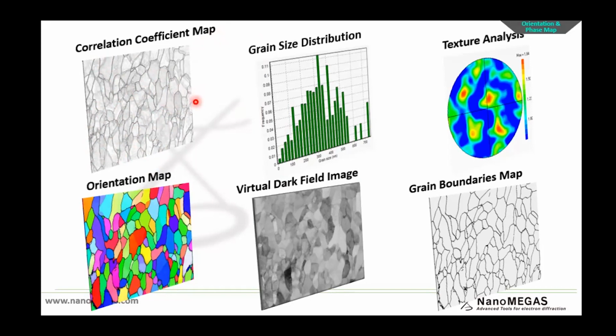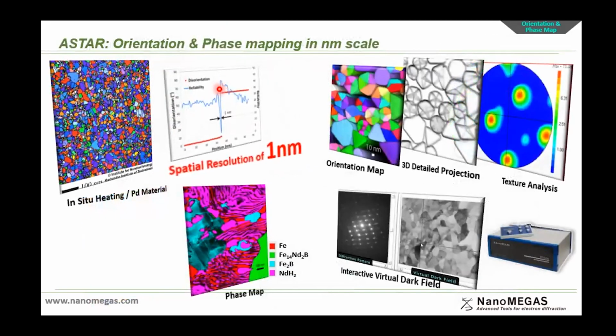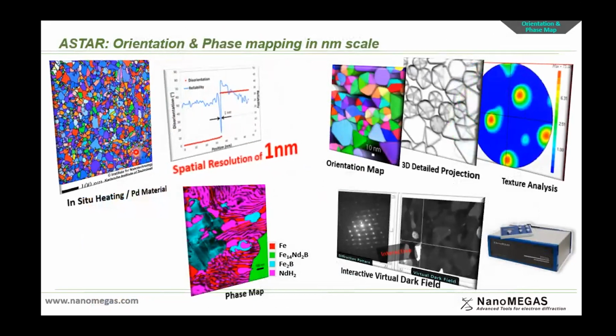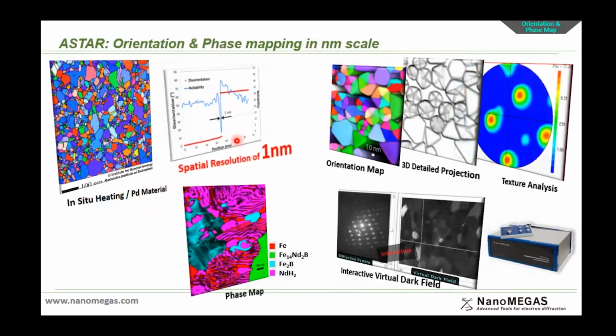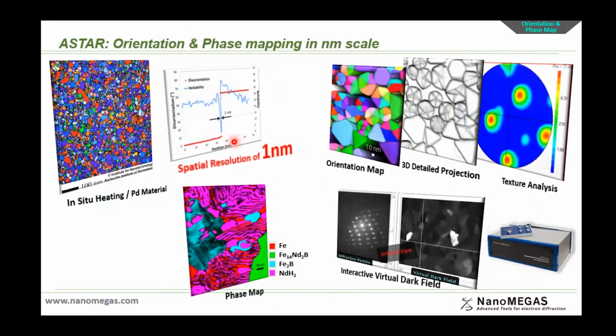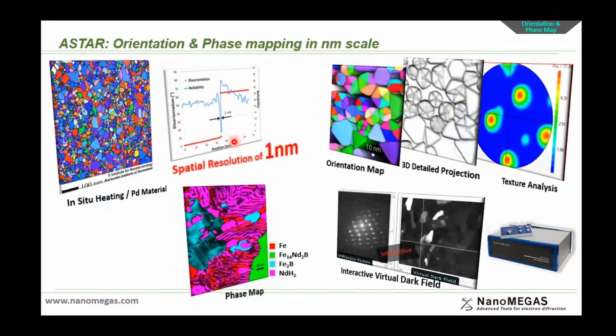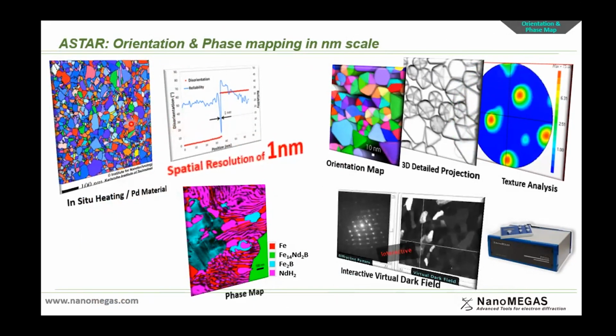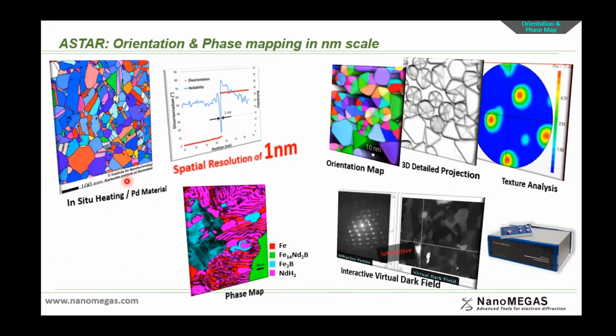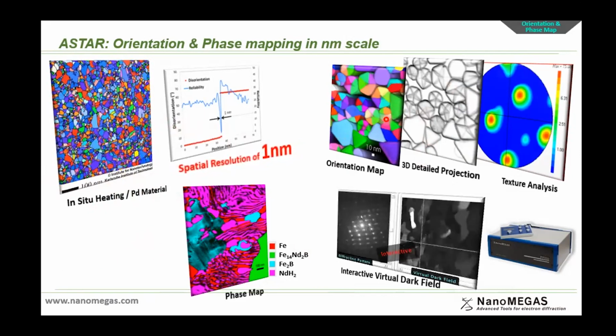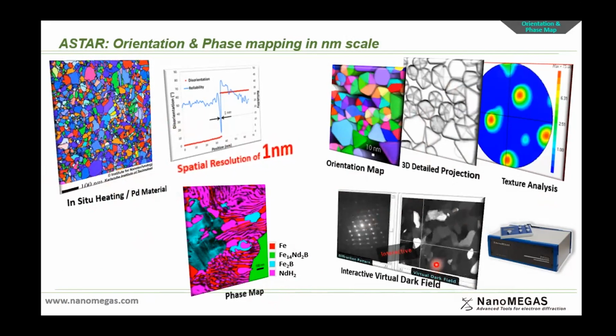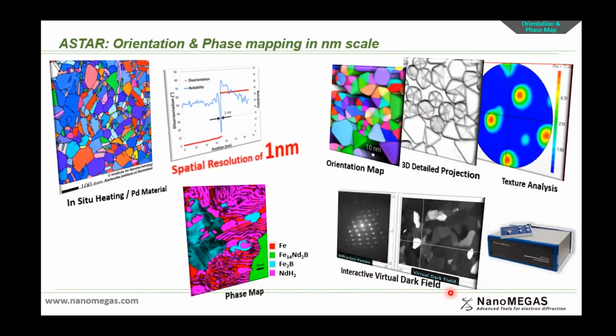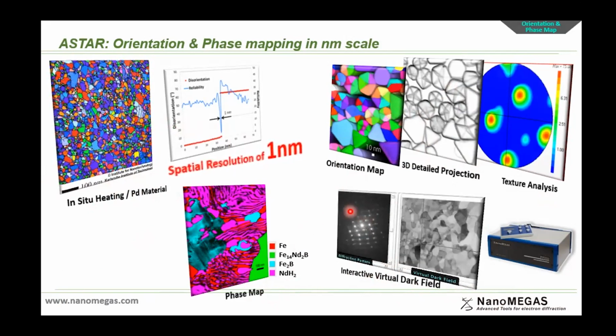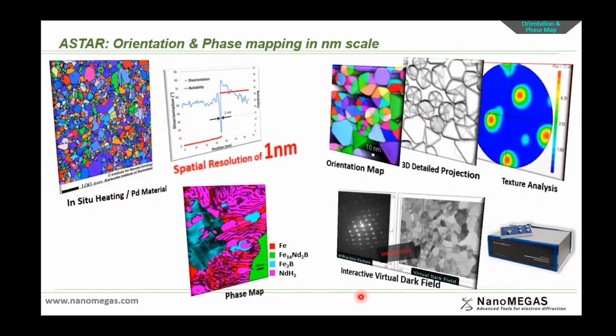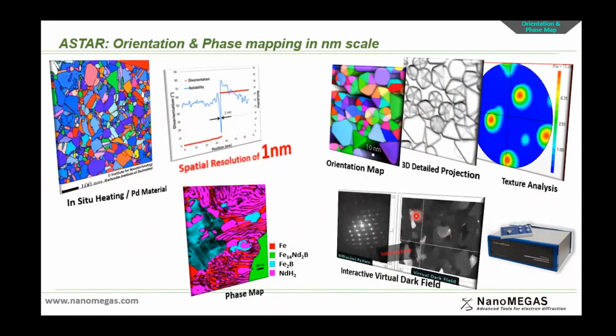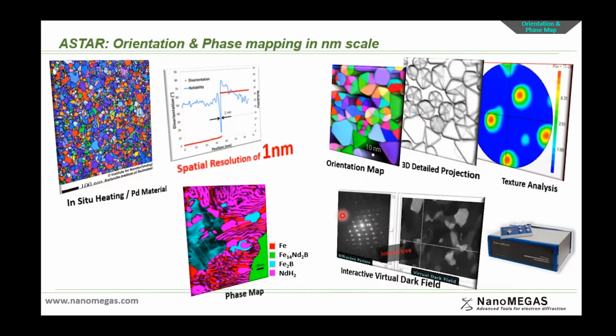Okay, this is what you obtain. The important thing here is that using a field emission gun transmission microscope, you can go down to a spatial resolution of 1 to 3 nanometers. The method is quite fast and straightforward, so it's easy to apply also for in situ experiments. You can have, as I said, an orientation map or a phase map. And this is another tool that is named the interactive virtual dark field that you can have for every pixel of your diffraction pattern series. You can have the virtual dark field image offline, just scanning your diffraction patterns, and you can see many local details of your sample.